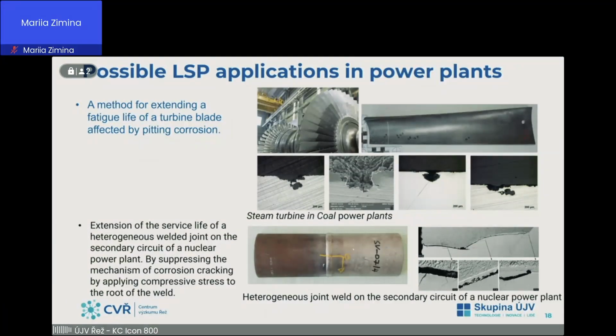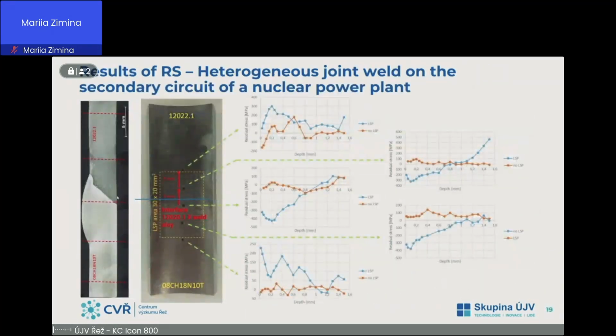Okay, and we tried treating the root of the weld and applied compressive residual stress to this area, where the crack initiation and then propagation occurs. There are first results from measuring residual stress before and after treatment by hole drilling.